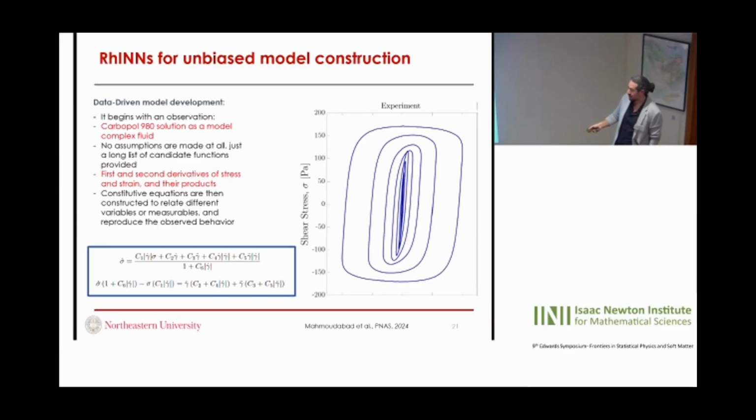So what we found was this. You have the time evolution of the stress as a function of basically 6 different groups. The coefficients don't matter, so you can rewrite it as this. Again, the coefficients don't really matter, but what's interesting is you have products such as gamma dot times gamma double dot, which is not exactly what you would see in a viscoplastic constitutive equation. So when I say teaching us new physics, maybe that's something we should pay a little more attention to. And by the way, if you get rid of this component, your predictions are going to be off.